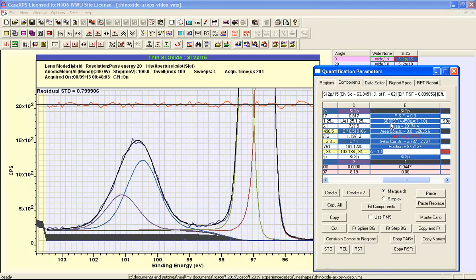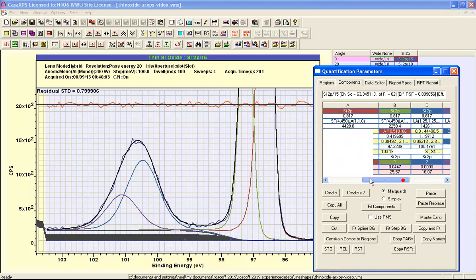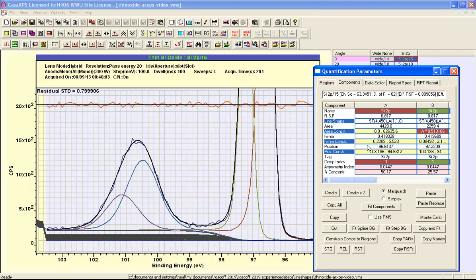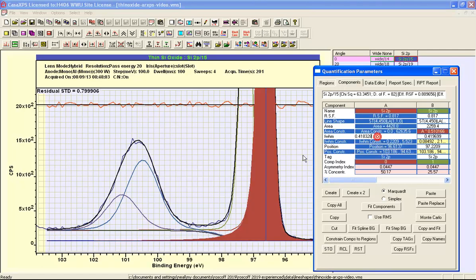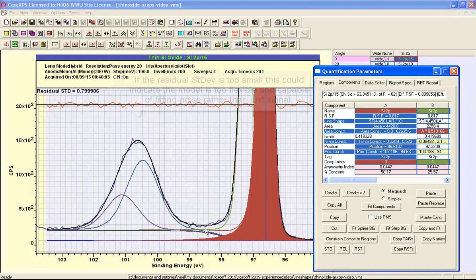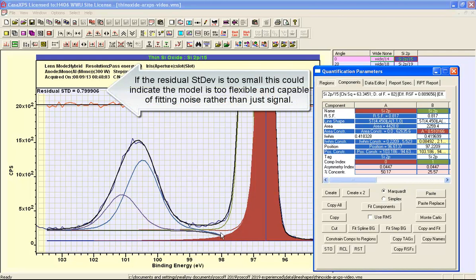You can also see there is a constraint here that has been introduced to produce an offset for this step in the background that is associated with the component in column A. And the component in column A is this peak here. So you can see that there is a means of introducing the concept of a semiconductor rather than a metal for this rise in the Shirley background.